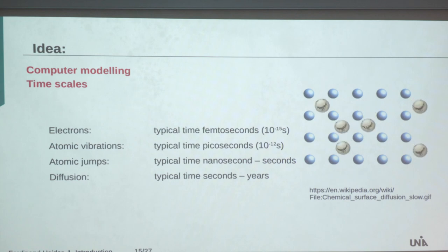Yeah? But still, if you want to sample these vibrations step by step in molecular dynamics, you must have time steps which are far smaller than these picoseconds. So typically you do molecular dynamics simulations with femtosecond time steps just to precisely sample these motions of atoms. Yeah.